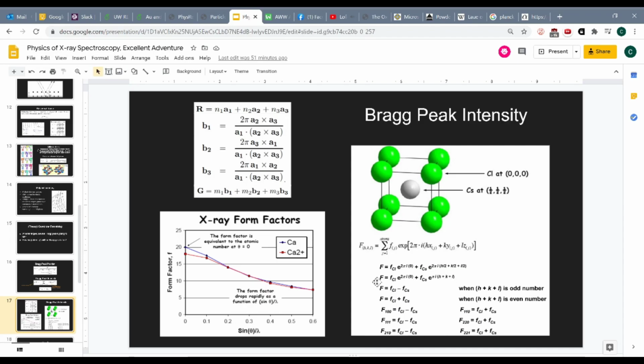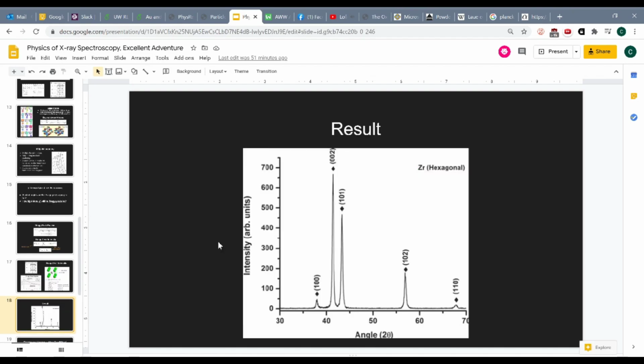So now we have a general form for what the structure factor is for any HKL value. It's easiest usually to input whatever atoms you have in your unit cell and calculate them in terms of the HKL values. Then when you want to figure out what the structure factor is for this unit cell for a particular plane at which the Bragg reflection is satisfied, you can input your HKL values. It gets complicated quickly. Okay, so we know our peaks, we know what angles they're at, now we can finally start measuring.